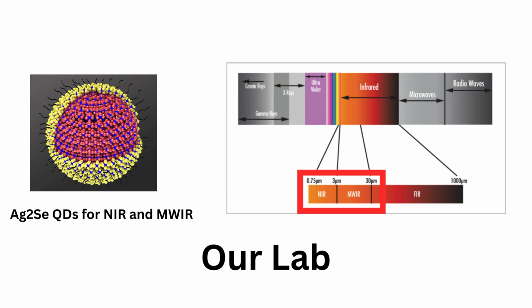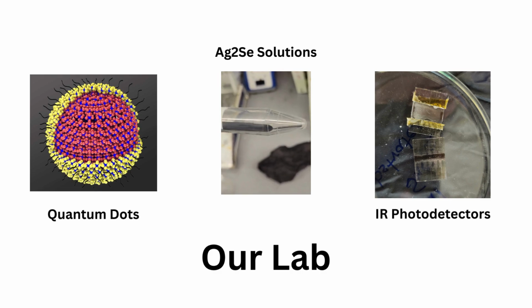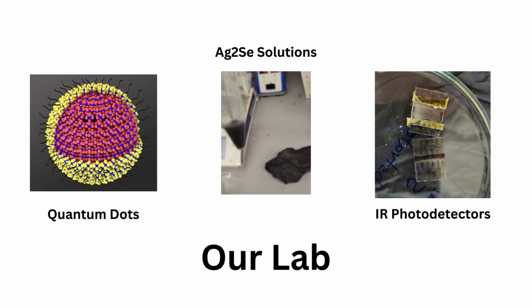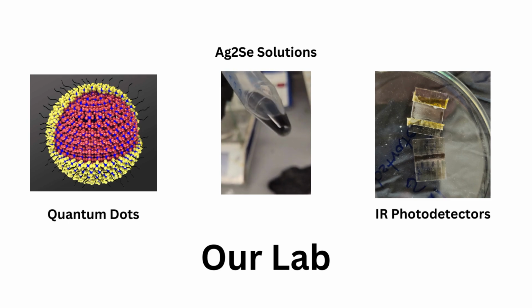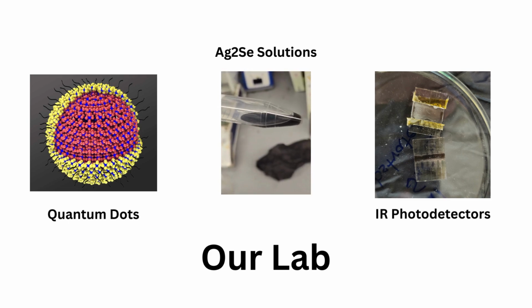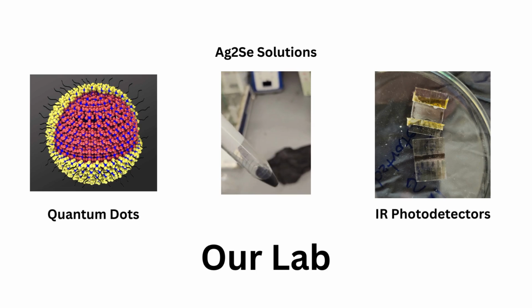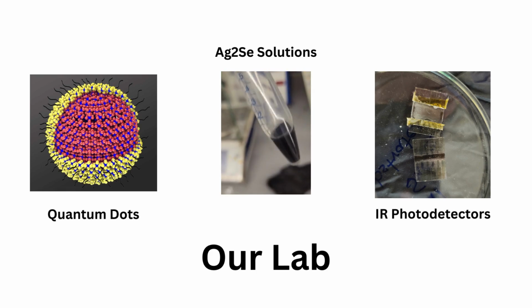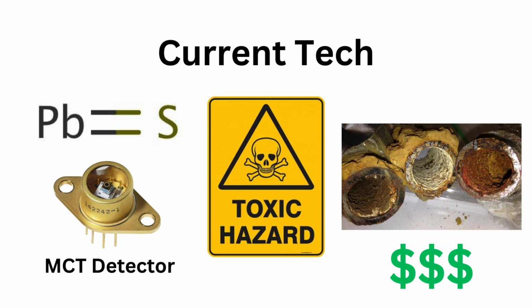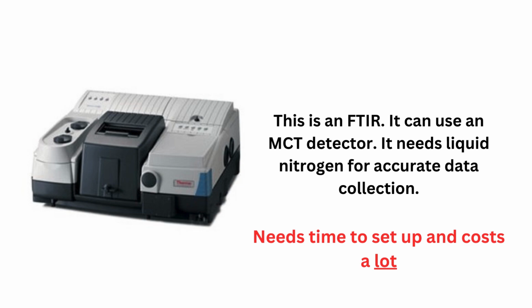We specialize in making low-cost, high-efficiency infrared light detectors using silver selenide quantum dots, which are microscopic semiconductor nanoparticles that can be suspended in colloidal solutions, allowing quantum dot films to be deposited on substrates, like how a printer deposits ink onto paper. The current forefront of IR detectors use materials like lead sulfide and mercury cadmium telluride, which use highly toxic metals. Furthermore, some of these materials need to be cooled down using liquid nitrogen to function properly. Their toxicity and need for cooling reduce these materials' accessibility and increase operating costs significantly.